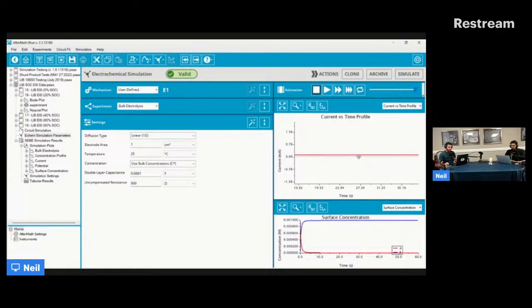And it's just because of the difference in the decay of the time constant. At any particular time, I'm at 5 tau right here on the first one, like immediately. But here I'm only at like 1 tau, and then I'm at 2 tau. And by the time I hit 4 or 5 tau, I'm at 90% with the other one, because of the time constant difference. It's just a difference in how quickly they are charging up, I guess. I don't know if that is a satisfying explanation, but it seems to fit from playing with these parameters here. I can increase this further and you see the difference gets even more stark.